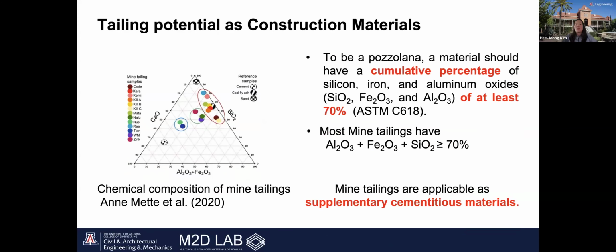If we look at the chemistry of mine tailings, most of them contain a lot of silicon, iron, and aluminum oxides, and some also have calcium oxide. This composition is very important for making cement. According to ASTM C618, a pozzolanic material should have at least 70% of silicon, iron, and aluminum oxide combined. Most mine tailings already meet these requirements. This means that tailings have good potential to be used as supplementary cementitious materials, or SCMs.